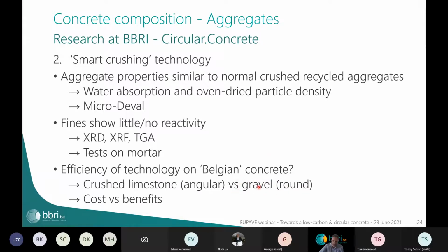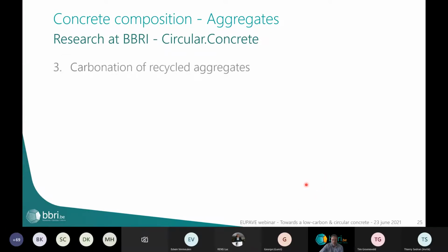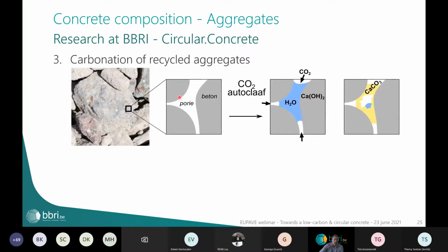And I can see that the technology can be more effective on rounded particles than on angular particles. And we also have to look at the cost versus benefits. What about the high quality streams that are already available? Is this technology useful to heighten the quality of those streams, or do the gains that can be expected not justify the higher costs of this treatment? So it seems a very interesting technology, but it has to be looked into if it's applicable on all types of recycled concrete. And thirdly, I want to talk about the carbonation of recycled aggregates.